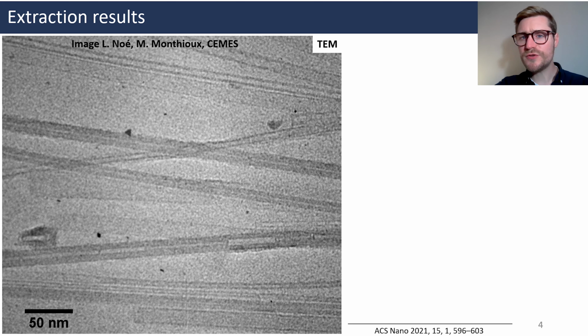Here, a transmission electron microscopy image of the solution after sonication. We can distinguish two kinds of objects. First, some multi-walled carbon nanotubes, as shown by the blue arrows. They typically possess an inner diameter smaller than 4 nanometers and an important number of walls. Then, the orange arrows emphasize objects having a smaller number of walls and much wider than the multi-walled carbon nanotubes, typically with a width higher than 5 nanometers. Those are flattened carbon nanotubes.